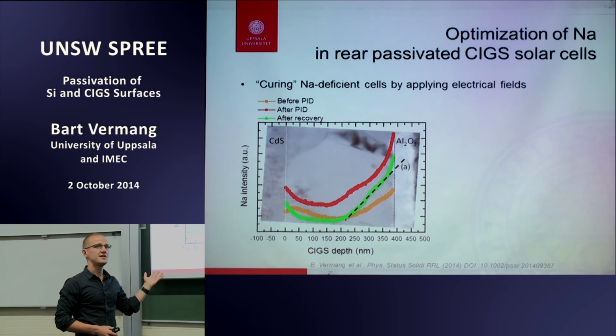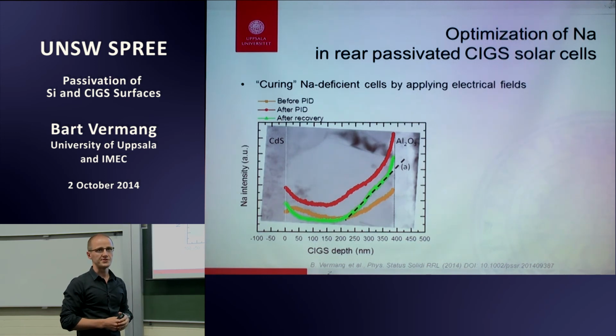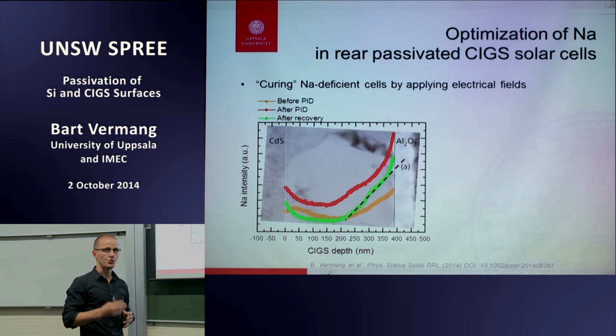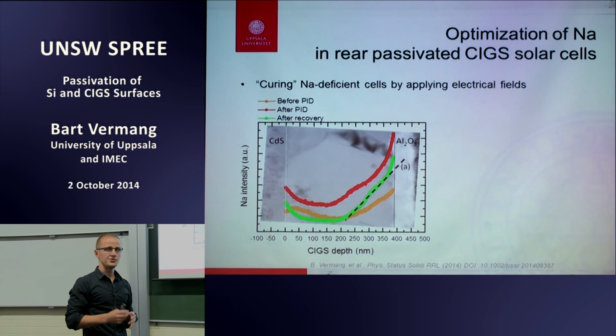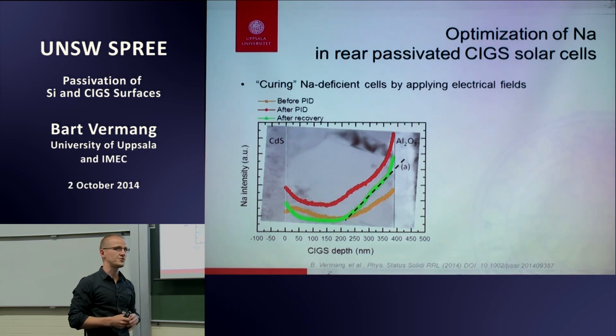The main reason they always say is, it's a debate, but it has to do with the dopants. The more sodium you have, the higher your doping can be in the CIGS layer, the more efficiency you can create. So you have too low doping if you don't have enough sodium. But that's a debate. So having that much sodium at the interface of the aluminum oxide, does that cause a problem for the passivation?